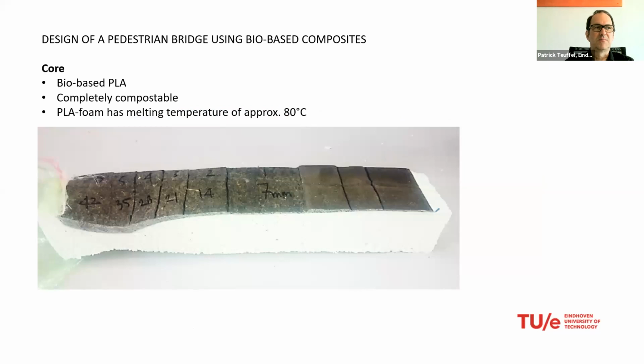And as the core, we used a bio-based PLA material. So that's a material which is completely compostable, but with the challenge that this material has a melting temperature of approximately 80 degrees Celsius. And the issue here is that during the hardening of the composite material, the temperature can increase above 80 degrees, which of course leads to the melting of the PLA foam, which of course causes problems. So for the production of the bridge, we then added additional cork interlayer as a kind of insulation between the hot composite material under hardening process and the PLA, which was used as a lost formwork.